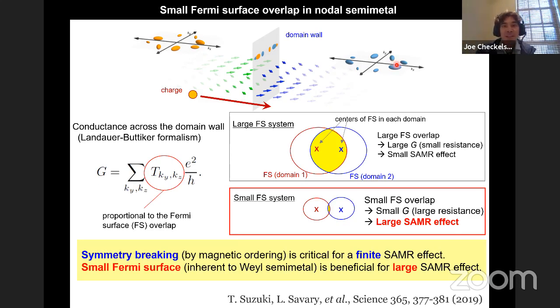And so when you imagine getting to a very nodal band structure, so here it's not so nodal, you imagine doing the quantum mechanics problem of an electron tunneling across this domain wall. As the Fermi surface becomes more and more nodal, you'll end up having a smaller and smaller overlap between these two domains, and the ability for an electron to move from one domain to the other will become more and more restricted, just from this picture of basically conductance across the domain wall.